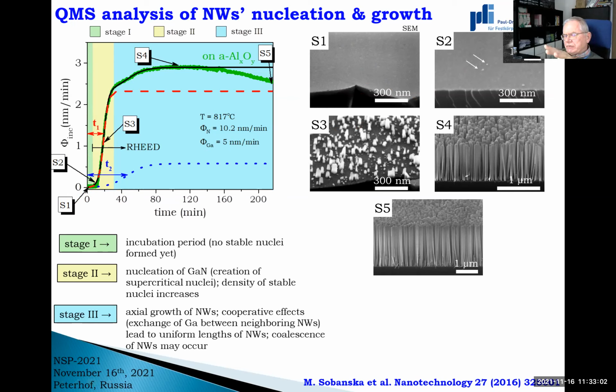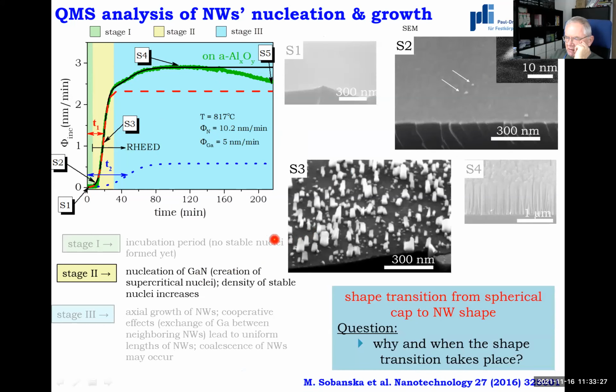This is the period during which gallium adatoms migrate on the surface, trying to create stable nuclei. Then, when the nuclei are stable, you see the first one appeared here, just at the very beginning. Then density increases. So this is the nucleation period, and then there is a period when these wires elongate, and next steps are in the game.